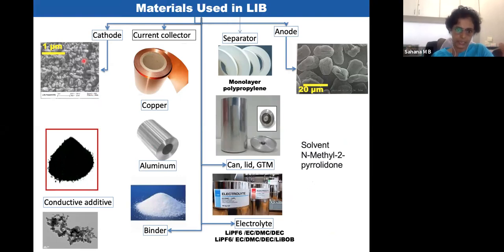As I told earlier, there is a left hand side here, the cathode. If you magnify that, you can see that each one of them is around 200 to 500 nanometer particles. This is an example for lithium iron phosphate. The active material is the one which participates in the redox reaction. That is, it gives lithium and electrons, and it takes lithium ions and the electrons. And the conductive additive, usually carbon black, is quite good electronically, which means it can conduct electrons from the current collector to the active material.